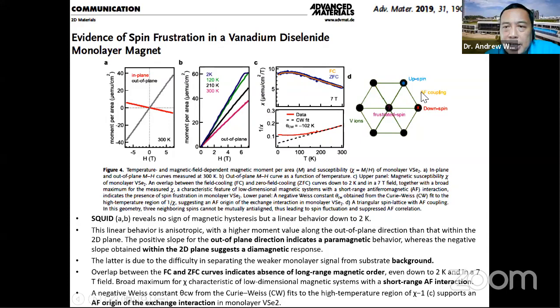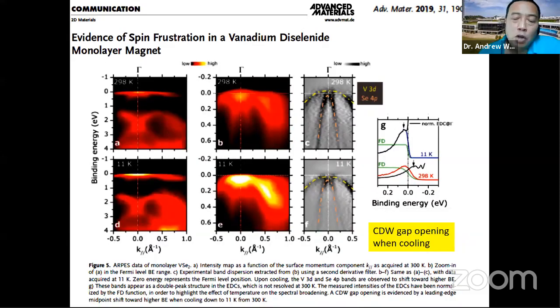And as illustrated in this diagram up here, you have these two spins which are anti-ferromagnetically coupled. But as you can see in this lattice arrangement, you have a frustrated spin in the center. It doesn't know whether to be up or down. So we postulated that vanadium diselenide is on the verge of being magnetic, but it's not magnetic. So that's spin frustration. This is further ARPES measurements that show the CDW gap when cooling. So that gives evidence for the metallic state.